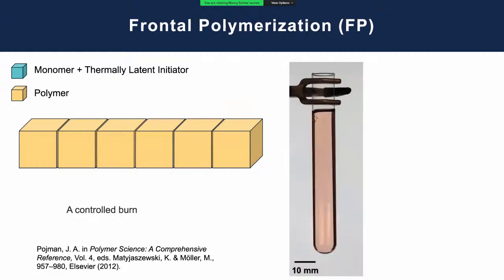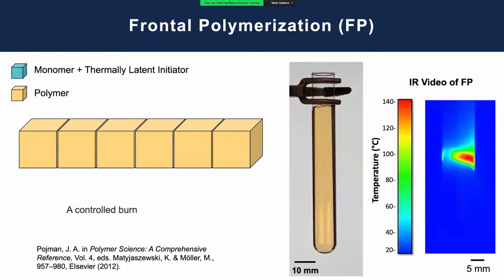Let me show you what this looks like in a test tube. A lot of frontal polymerization work goes on in test tubes. This is the monomer - you're going to see a color change as it polymerizes. What you don't see here is a small soldering iron coming in that's the heat source. The heat source is taken away very quickly and you see this nice smooth front propagate. You get this nice cure front of conversion of monomer to polymer.